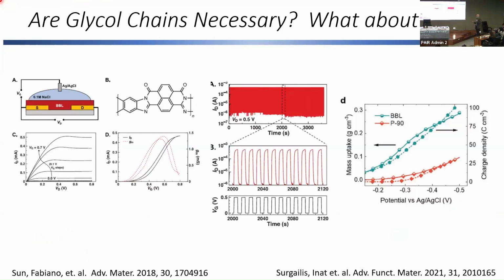But there's some work on other polymers where they don't have any glycol chains. BBL, for example, is a polymer where you have no glycol chains. And you say, well, I told you earlier you need glycol chains for solubility, for example, to be able to deposit these materials. This polymer can be fabricated in a thin film from concentrated acid. So it's not ideal. Some substrates don't work with this.